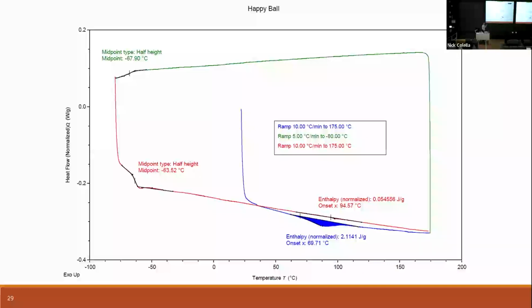So we see here, we have some crystallites that formed when this rubber ball was formed. And then we see this onset of melting right around 70 degrees. On the second curve, we've erased those crystallites. We've melted them and they didn't recrystallize on our slow cooling. So we've done some characterization and some modification of the system. So anytime you take what that ball is made of, the second heating cycle should always look like this.